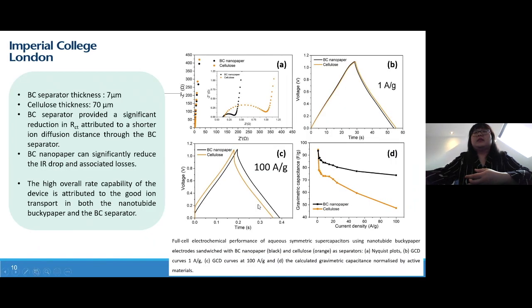So fabricating the cell device, I compared different separators, the conventional cellulose against the BC nano papers. It shows that at low current density the performance is almost similar, but it shows more obviously at high applied current density, which commercially we generally need to apply to be suitable for electrical applications. In that case, the BC separator shows better performance and better rate capabilities, with very high capacitance up to 100 amperes per gram.